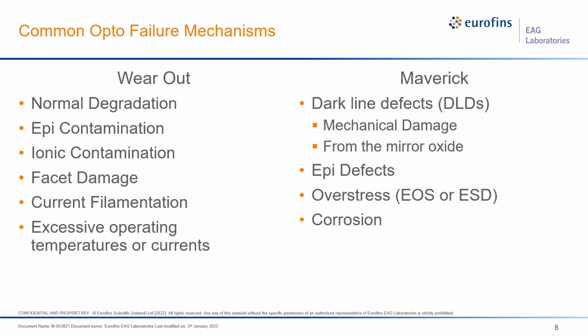They've been made quite reliable by careful design and screening, but aren't inherently reliable. There are two main types of failure: wear out and maverick. Wear out failure is typically a gradual type of failure. It's a part that fails due to something that's consumed until it can no longer do its job properly. Whereas maverick failures are typically abrupt and have some sort of defect incorporated into them, with much worse lifetimes than others from the same batch, and fall well outside the 95% confidence limits for the bulk of the population.